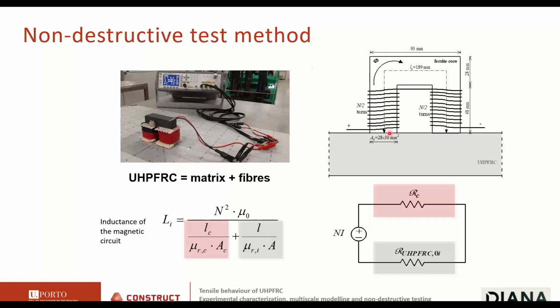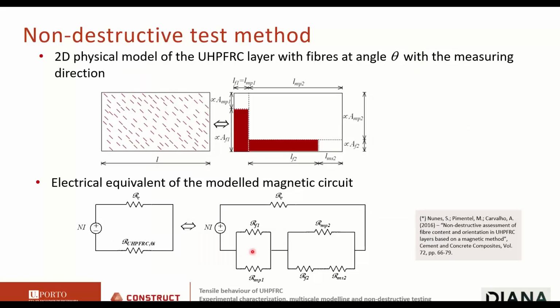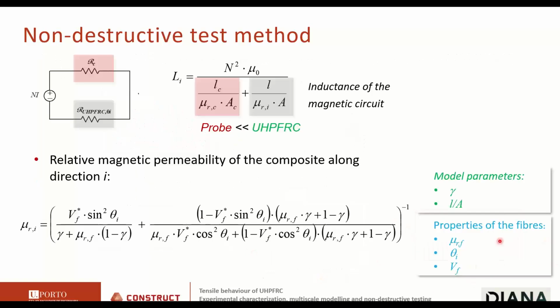The probe is basically a ferrite core with some copper winding on which we introduce an electric current that generates a magnetic field. The magnetic inductance of this magnetic field can be measured with this device, and it can be analytically expressed by this equation. The complex thing here is the determination of the relative magnetic permeability of the composite. So we developed some models to have an estimate of a theoretical value for the relative magnetic permeability as a function of the fiber orientation. This is described elsewhere.